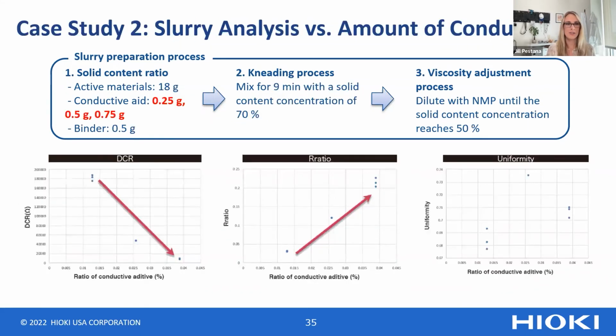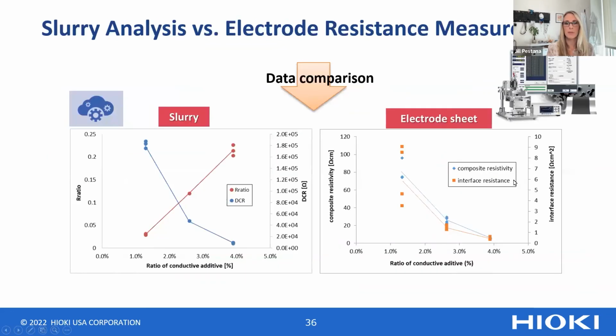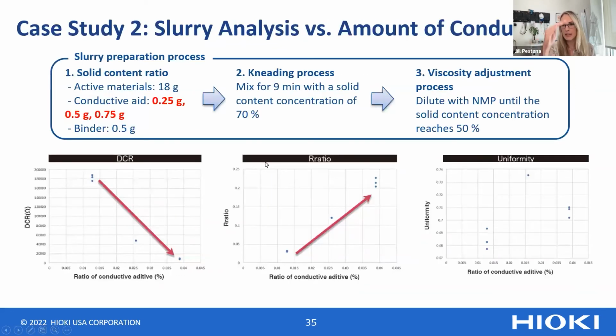The second demonstration is changing the solid content ratio, specifically of the conductive aid or conductive additive. And of course, as you increase that conductive additive, in that graph on the left, you decrease the total resistance. I mean, that's intuitively what I would think would happen. Also, you increase that R ratio as you add in more conductive additive. But this uniformity, check out, this is different. It first starts pretty low and then it increases for that middle point and then decreases for the last point. So as you add more conductive additive, you get this more ideal capacitor situation, followed by, oop, I went too far, it decreases.